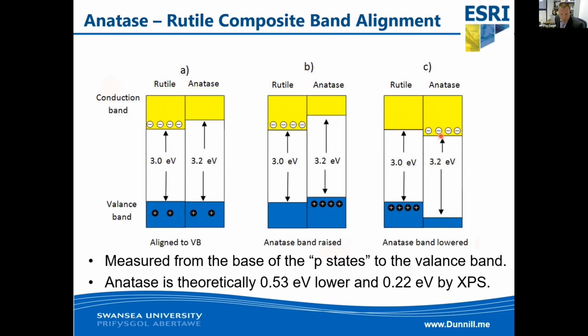And this is actually really quite important because in the combined synthesis of anatase and rutile, it's quite important which one is the oxygen catalyst and which one is the hydrogen catalyst, or at least which one is the oxidizer and which one is the reductant. So that answered quite an interesting question, and got us a paper in Nature Materials, led by Scanlon, who did the computational work for this. I think that's now had 1,700 citations since 2013. So it's actually a really quite nice paper.